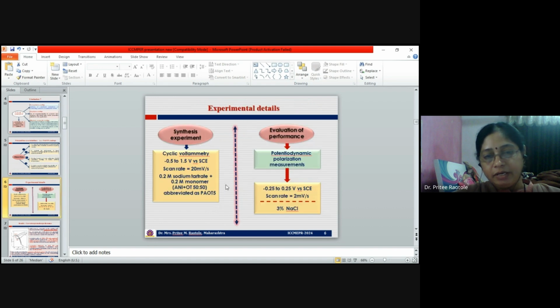In experimental details, the coatings were synthesized by cyclic voltammetry by sweeping the electrode potential from -0.5 to 1.5 volt at the scan rate of 20 millivolt per second. The corrosion protection performance of these coatings was evaluated by the potentiodynamic polarization measurement by sweeping the electrode potential from -0.25 to 0.25 at the scan rate of 2 millivolt per second in 3% NaCl.